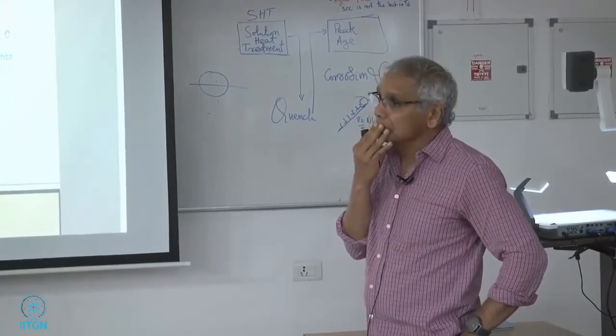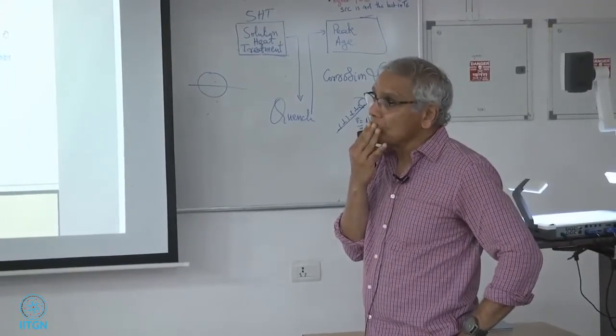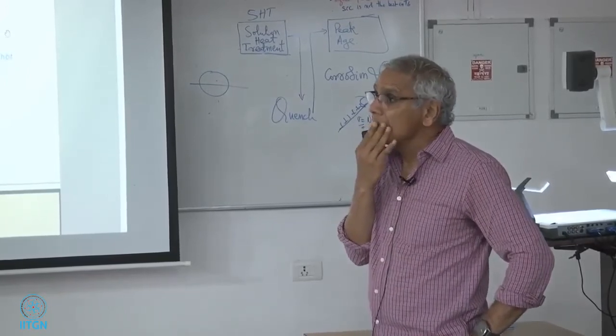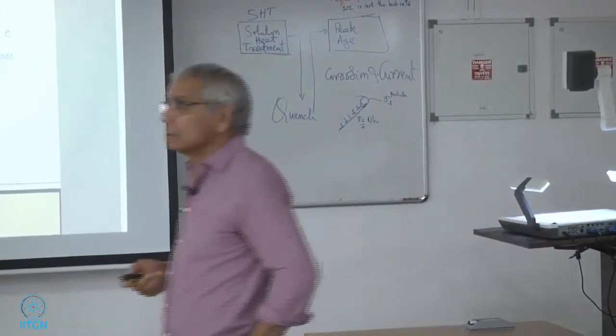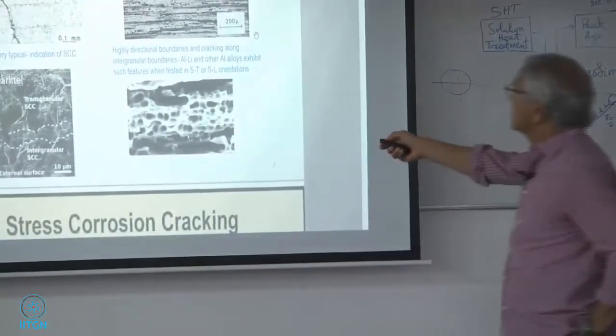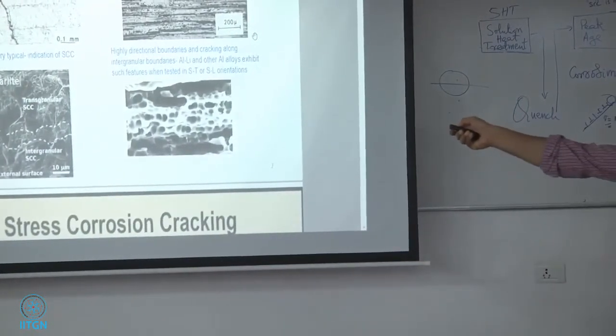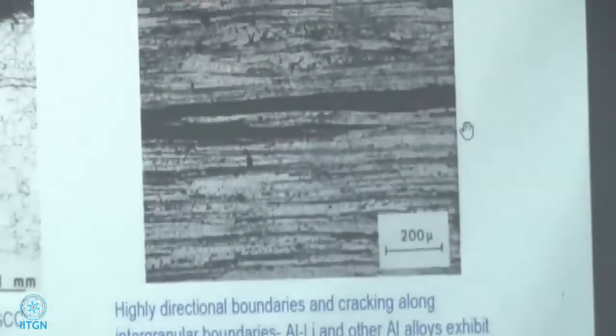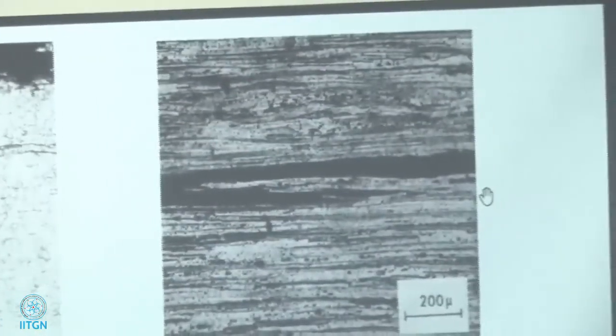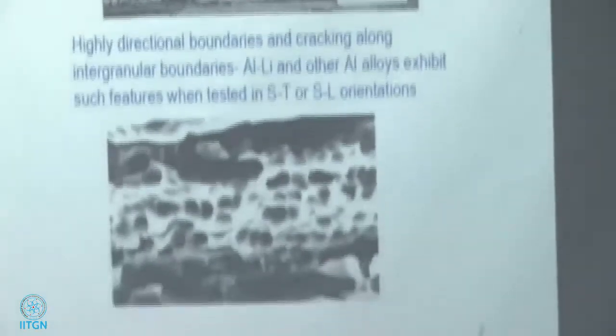So a lot of times what we do is, if this is your fracture surface, we put something on top of it to protect the surface from deforming when you polish it. What do you put? Nickel plating. So you have to put a nickel plating here and then polish it, to avoid the rounding of the surfaces.